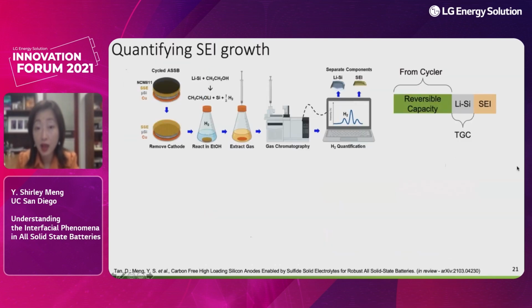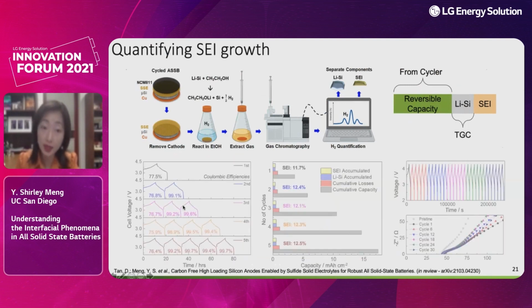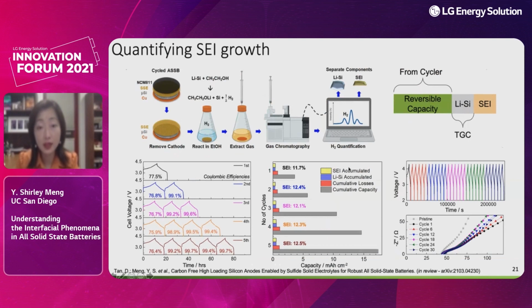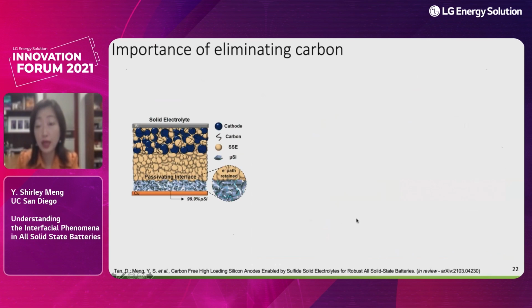So it should work. We've also previously shown the field a titration gas chromatography method that can differentiate trapped metallic lithium versus SEI lithium, and we utilize this tool in our silicon research. Oftentimes we found the SEI after the first cycle actually stops growing, because the cell's coulombic efficiency very quickly rises up to 99 and above, and in some cases can reach 99.9. This method is very helpful for us to gain confidence.